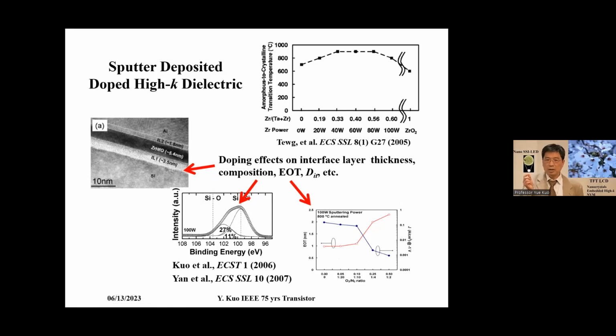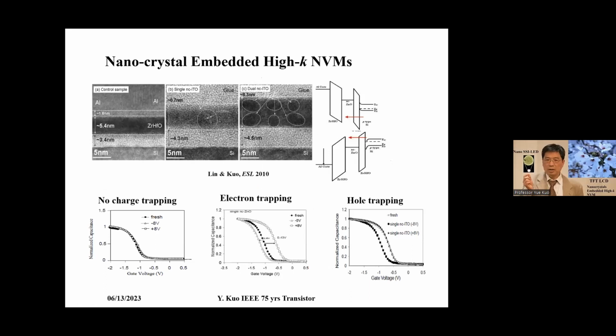That's another example. Based on that, we keep the high-K dielectric in the amorphous state. Then we can embed another layer. Then we use rapid thermal annealing to heat up the high K with the embedded layer. Then we form embedded nanodots, nanocrystals. So in that case, it becomes non-volatile memory. The charges are injected into the gate dielectric and retained there. And the retention can be more than 50% after bias stress, extrapolated to 10-year equivalent.